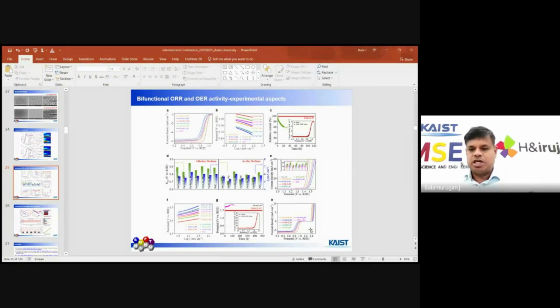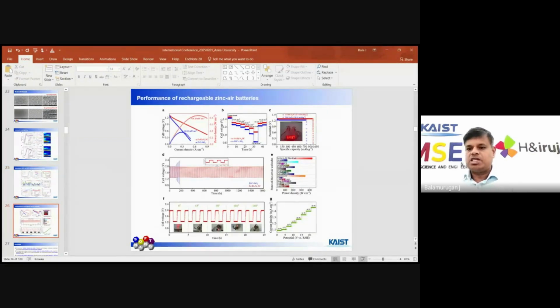So after confirmation, we do the fabrication of the zinc-air battery. We get higher stability, more than 1600 hours, and we also achieved a high peak power density, which may be 2.5 times higher than the commercial catalyst. On rate performance, when increasing to higher currents, the reversibility is better for our catalyst, but in the case of platinum-iridium, it is not as good.